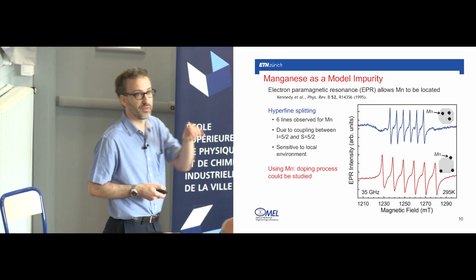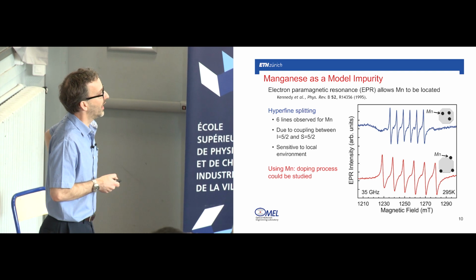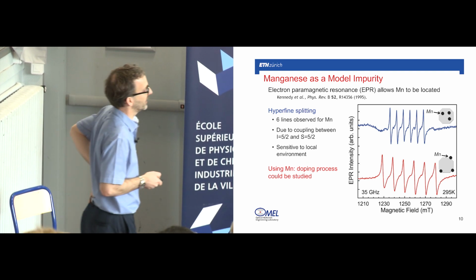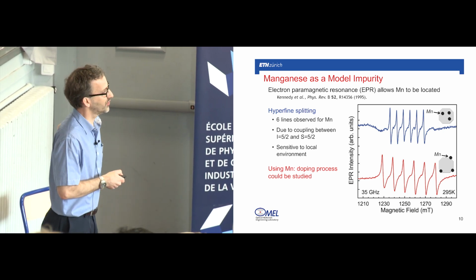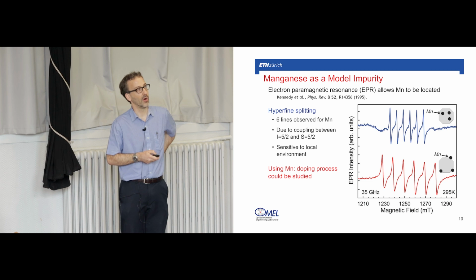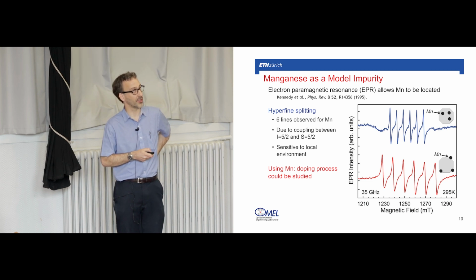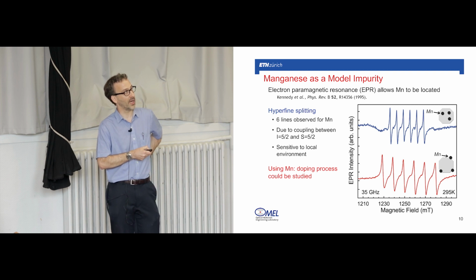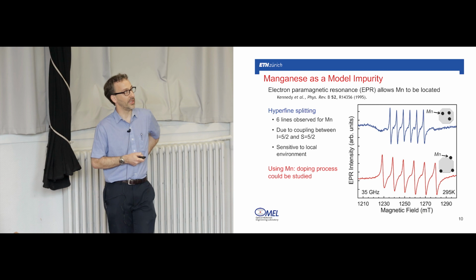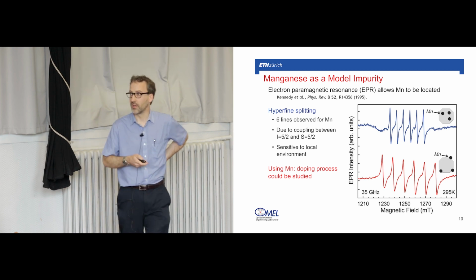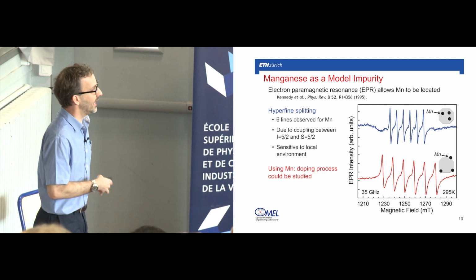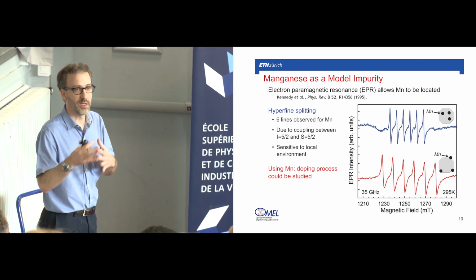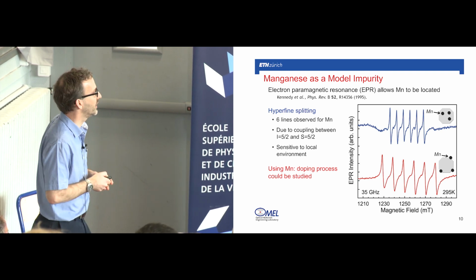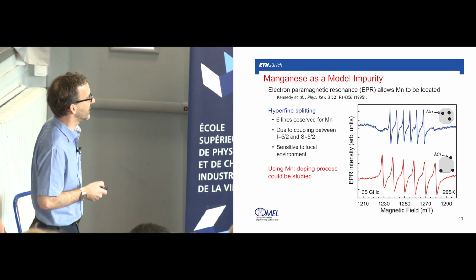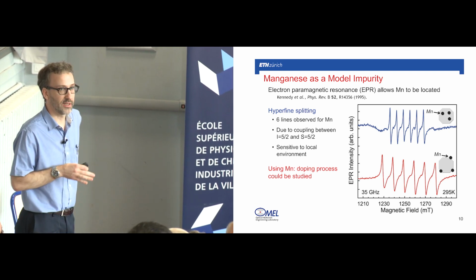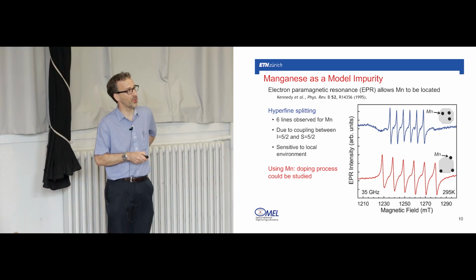I mentioned that it's very difficult to find techniques to determine where the impurities are. But with EPR spectra, and I'm showing 2 typical EPR spectra here, you can very clearly distinguish spectra where the manganese is on the surface or on the interior, inside the lattice of the semiconductor. This is because these EPR spectra are governed by hyperfine splittings between the nuclear spin of the manganese and the electronic spin, and this hyperfine coupling is very sensitive to the local environment. And of course, at most universities, somewhere, maybe in a basement, there's an EPR spectrometer. So you can easily do these measurements and determine where your manganese was. So using manganese, even though it's not electronically active, as we'll discuss, the doping process could really be studied and understood.